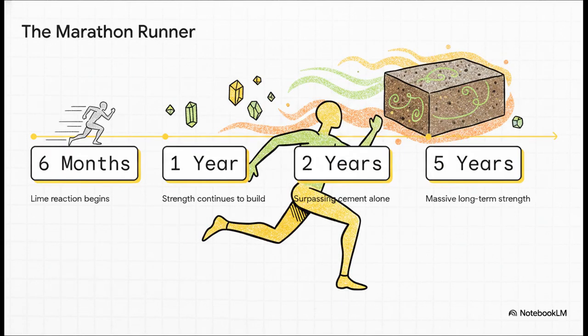But as the timeline accelerates from 6 months to a year, 2 years, and all the way out to 5 years, well, the marathon runner enters the chat. The lime begins a slow, continuous pozzolanic reaction. Over months and years, the lime raises the pH of the moisture in the block, dissolving the silica and alumina in the clay to form incredibly strong calcium aluminosilicates. It's this beautiful slow burn that just continues to build massive long-term strength, long after the cement has finished its sprint.